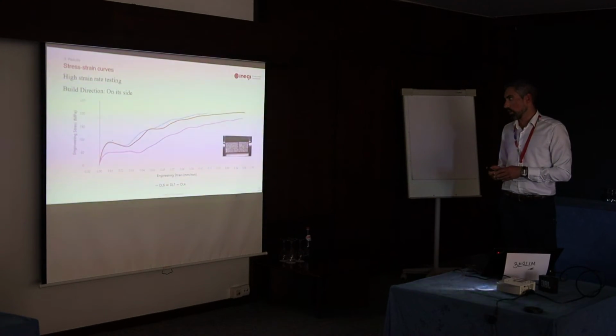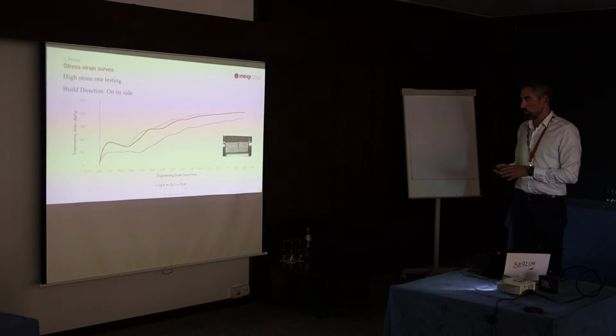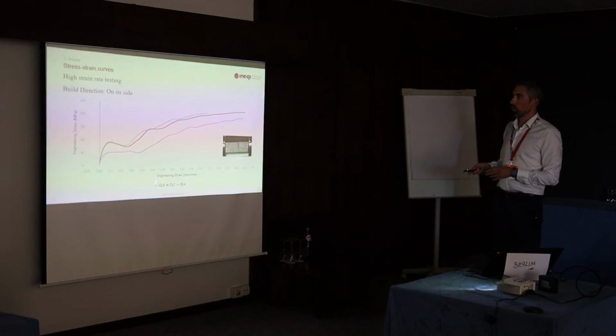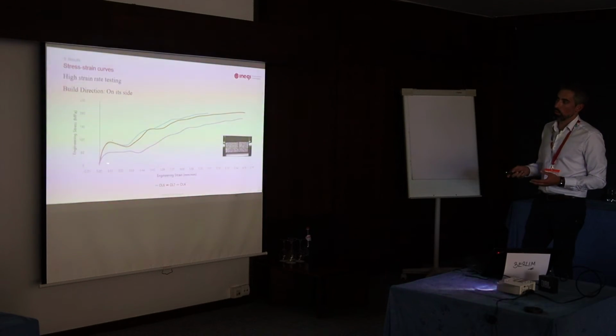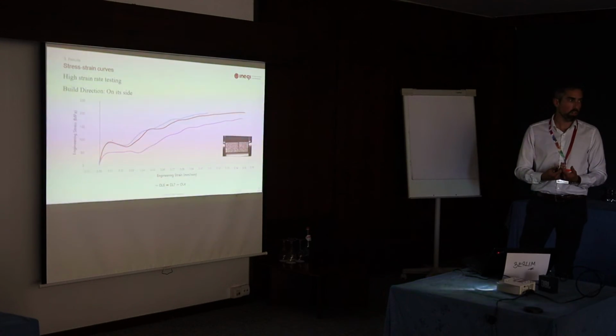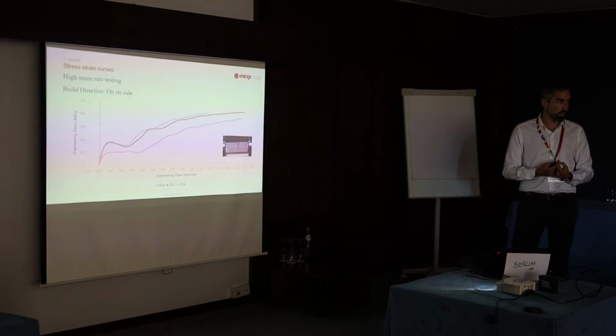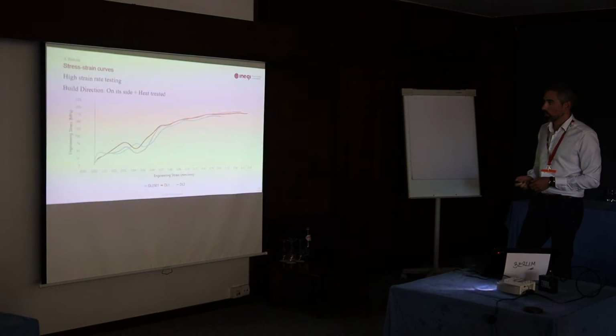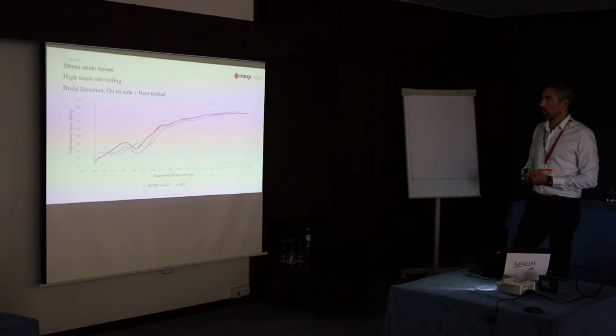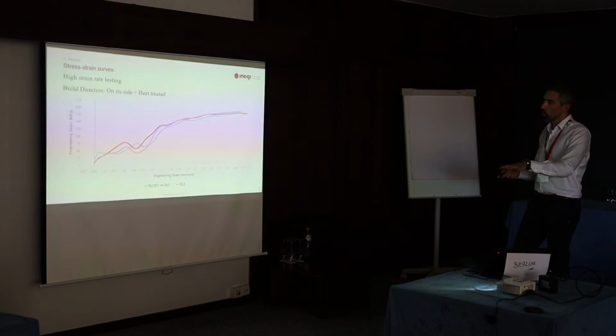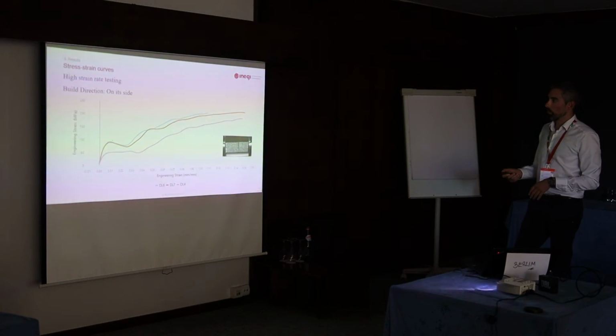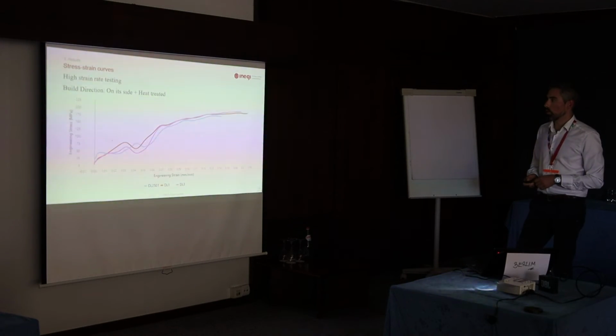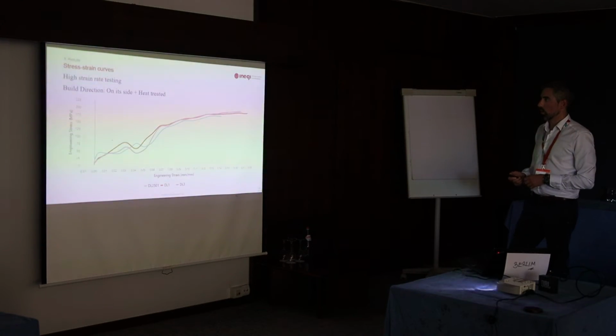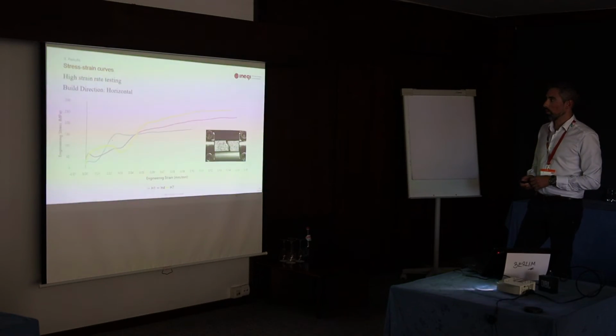For the on-site building direction, the fracture also varied slightly, and how the material responded to the initial instantaneous phase of excitement was also different. The propagation was smoother than in the case of the vertical building direction. Here was plus the heat treatment. You can see that there is a smoothing of the initial phase, but the overall end result was very similar, so not a big effect here.